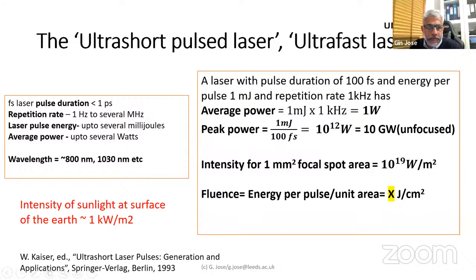So this is typically coming from some of these definitions around average power, peak power. If you look at a laser which has an average power, it's calculated using its energy per pulse times its repetition rate. It's around 1 watt, but that same laser has a peak power, the power per each pulse, of around 10 gigawatt. So if you focus this laser down to, say, a millimeter square focal spot, then you're getting huge power, which is 10 to the power 19 watts per meter square.